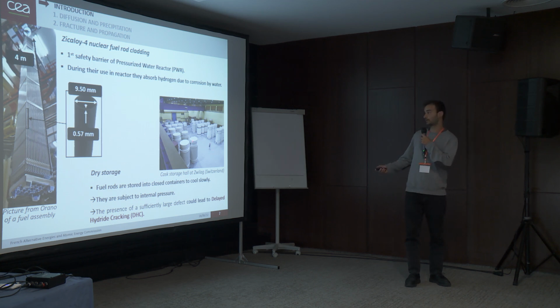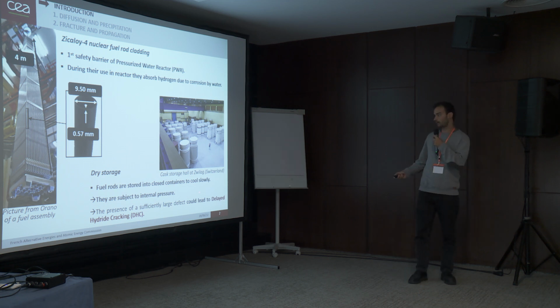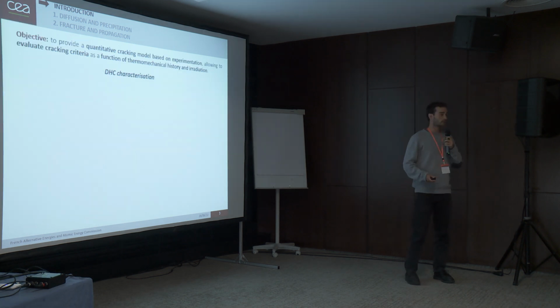And you can see a picture here of cask storage in Switzerland, so you have already seen this picture. The fuel rods are stored in a closed container to cool slowly, and they are subject to an internal pressure, and if a sufficiently large defect exists in the material, it could lead to delayed hydride cracking, or DHC. So our objective is to provide a quantitative cracking model based on experimentation, allowing us to evaluate cracking criteria as a function of thermomechanical history and irradiation.